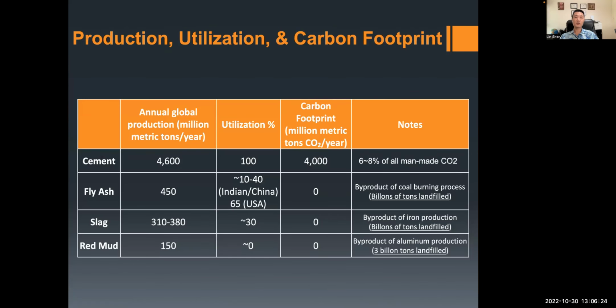And this table shows the production, utilization percentage, and carbon footprint of cement, fly ash, slag, and red mud. Because fly ash, slag, and red mud are waste materials, they will not have any more carbon footprint when they replace Portland cement. And because of the low utilization percentage, right now we have billions of tons of fly ash, slag, and red mud landfilled already.